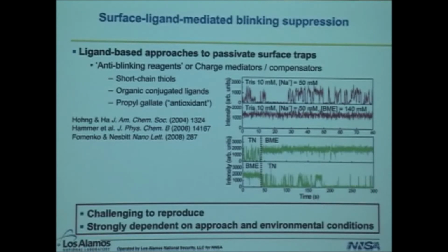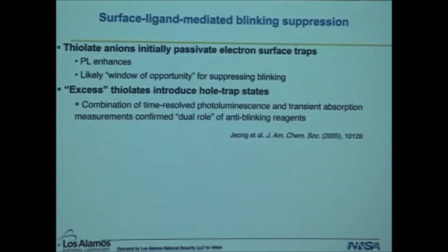However, it turns out that this type of approach was difficult to reproduce in the community, and it was found by us and others to be highly dependent on how you approached this process and how you stored your quantum dots. More specifically, what we found out was that, for example, in the case of thiol molecules, it turned out to be the thiolate anions that were able to initially passivate electron surface traps, and that indeed enhanced your optical properties. The PL efficiencies went up, and you had a short window of opportunity to suppress blinking. But unfortunately, when you applied additional thiolates, and it was hard to determine when that happened, you ended up introducing trap states, in this case hole traps.